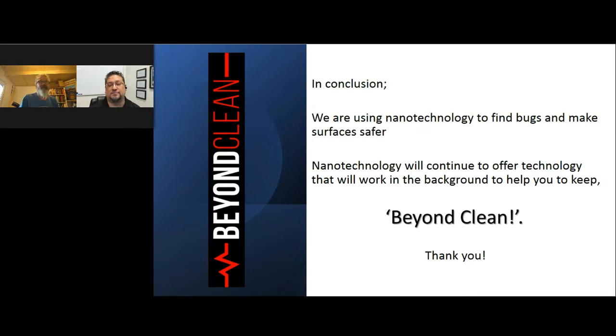As long as we have a cleaning regime that keeps the surface clean, it will remain actively antimicrobial. And because we're using a PVD technique, the coating is actually extremely thin. Typical coating thicknesses are about 1 micron or less. But because of the durability and the cleaning we do, it's not like a typical coating. We essentially bind the materials together atomically, and that's why it's such a good coating.